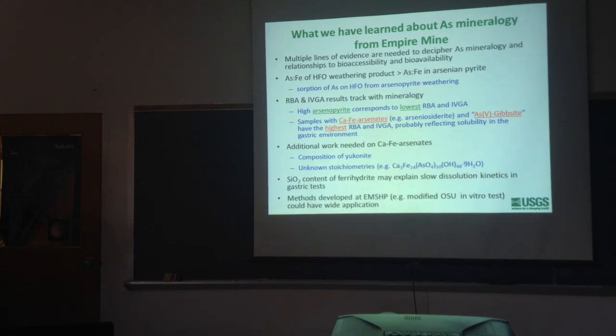One thing I didn't mention but came out was kind of interesting in our studies. Every time we used electron microprobe to get a quantitative concentration in ferrihydrite, which is the hydrous ferric oxide, we always got 1% silica. At first, we weren't sure it was really there, but we looked in the literature, and it's pretty typical to get 1% silica in an iron oxide like that. We think it explains why so little of this HFO material dissolves in the stomach fluids.